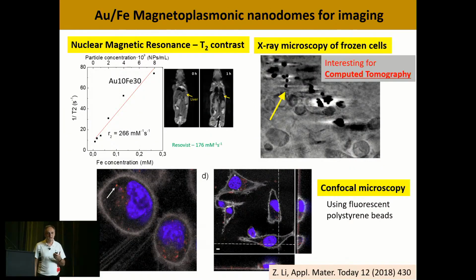And actually, these nanoparticles can also be used for biomedical imaging. Here I show you some magnetic nuclear resonance, T2 contrast. You can see here the T2 signal, and we have an R2 of about 266, which is, I don't know, 50 times, 100 times larger than the commercial iron oxide nanoparticles.